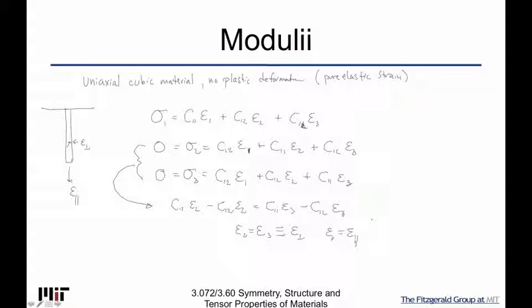So, now I'm going to go back, I'm going to make these substitutions, first of all, into this expression up here. And one of these expressions, let's say the second one, what the second one is going to produce just by itself, because the minute that I substitute in these, I can actually solve for epsilon parallel in terms of epsilon perpendicular, just with this middle expression here. And that's going to give me Poisson's ratio in terms of C's. And then, once I have the relationship to epsilon parallel and perpendicular, I can come back and substitute in here and solve with the sigma that I have, and that'll give me Young's modulus, which are all under the unique case of uniaxial stress. So, let's do that.